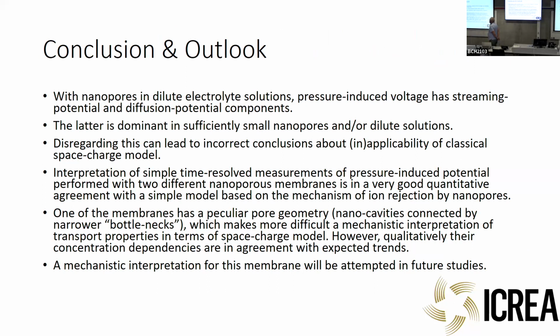So basically, I think the principal conclusion is that the pressure-induced electrical response to pressure in nanopores is actually dominated often not by streaming potential, but by concentration or diffusion potential. And this is seen in time-resolved measurements, which are not terribly complicated, but you need to know that they are needed, so to interpret results in a correct way.